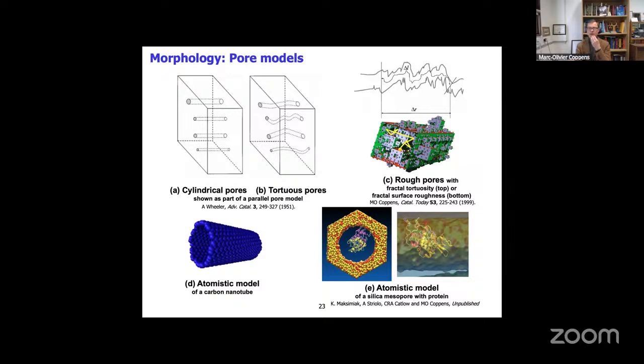And then we can invoke furthermore also the roughness of pores. This is something we looked at, and this area is very close to my heart. It's something which goes back to my own PhD thesis work, which you'll see something back from later, which involves surface roughness. The fact that pores are generally not smooth, but that our imaging methods and X-ray scattering techniques and so forth tell us that these materials are rough, and that we therefore should look at whether this roughness has an impact on diffusion.